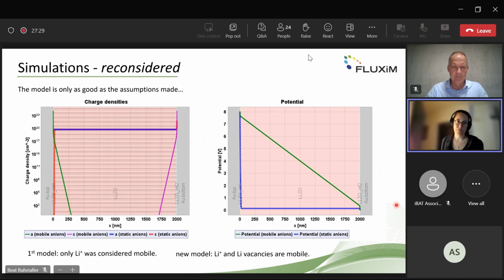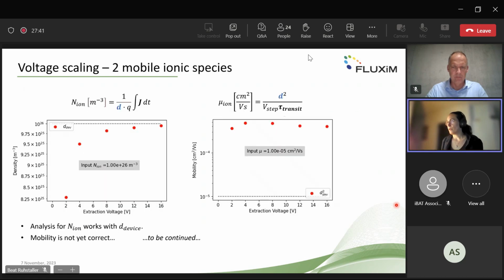We get this accumulation of charge carriers, ions, at both electrodes, and also we still get a field that drops over the full device. So if we do that, we also see that now the analysis works with this device thickness. So now we change the extraction voltage and we really approach with our analysis the theoretical maximum. With the mobility, we are not yet there, but this is really work in progress. So I think we can also move there.